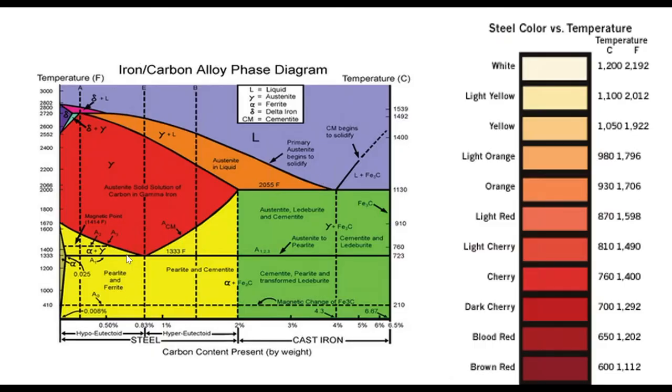The reason we can do that is because steel is really iron and carbon, and we have a really unique opportunity right here. Most of the steels that we make are between 0.1 and 0.4 carbon content. If I take that at room temperature, it can only hold inside it 0.008% carbon. At room temperature, it's got to make carbides. That carbon can't stay in solution.